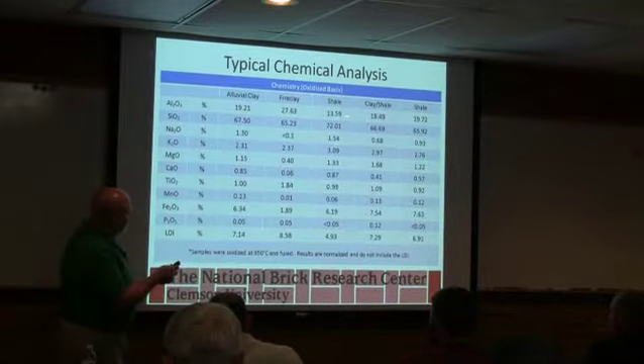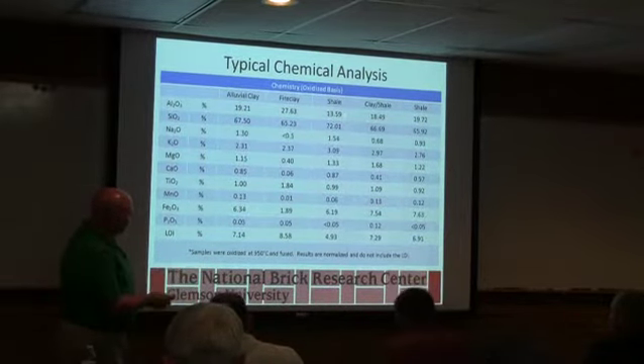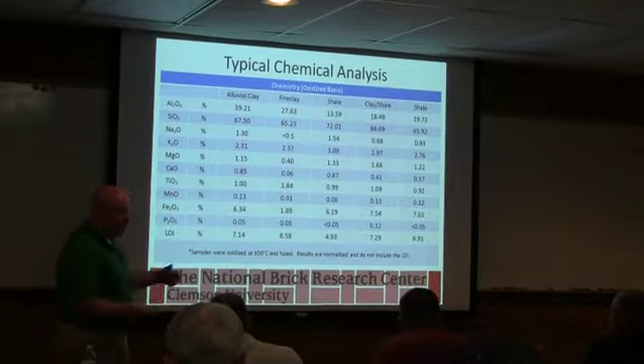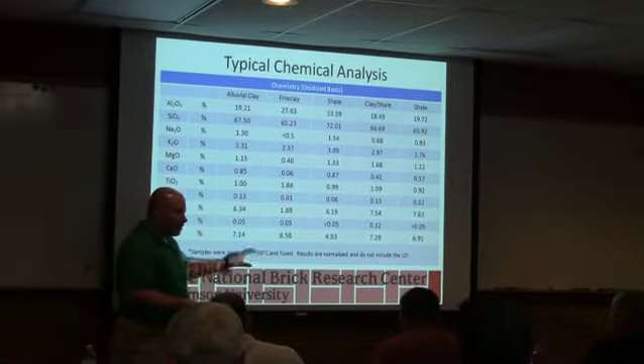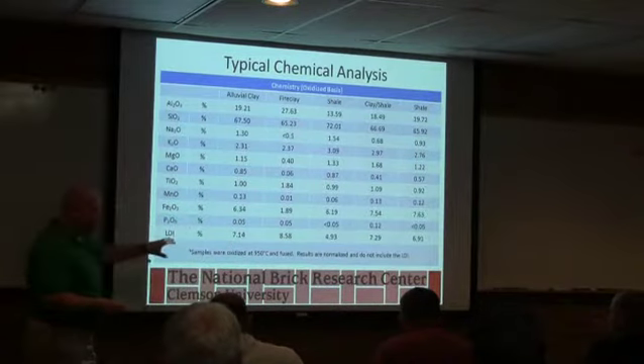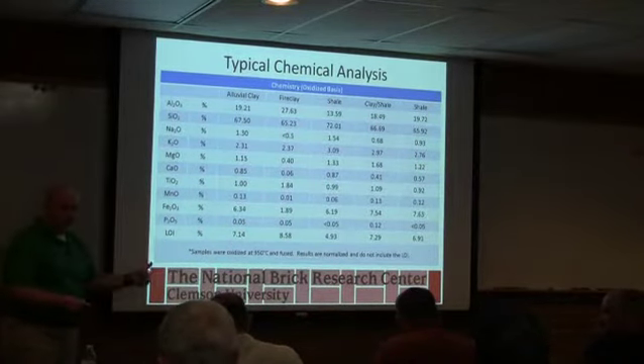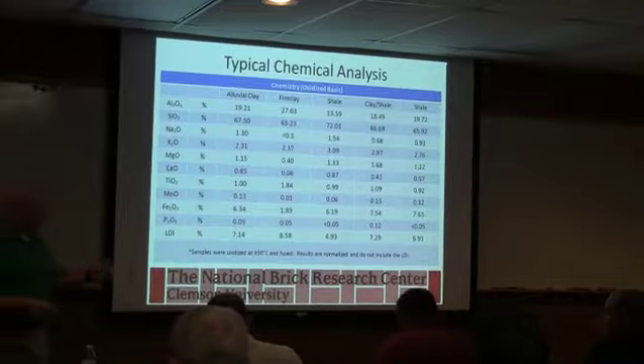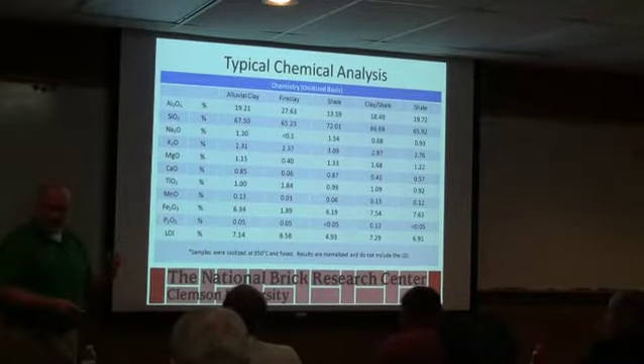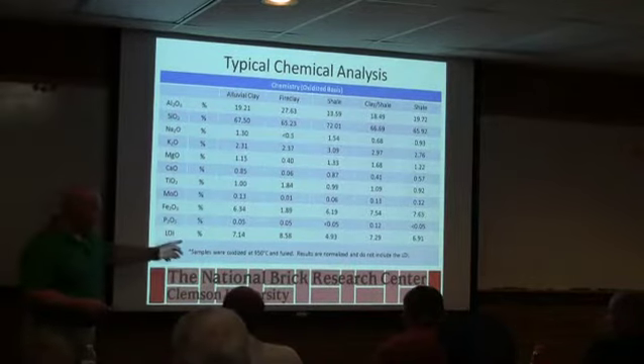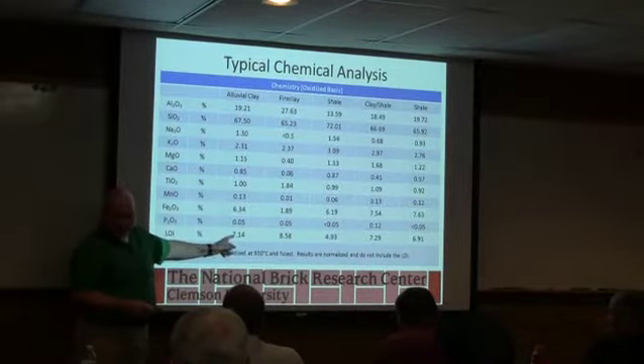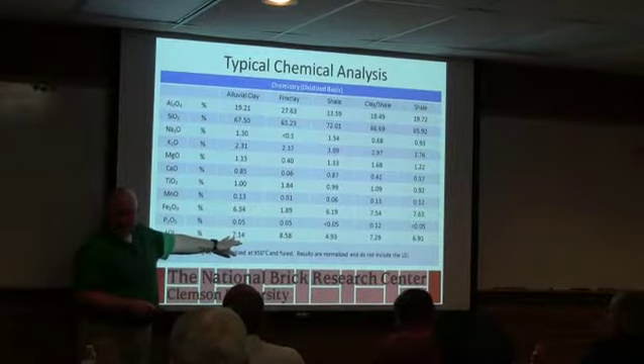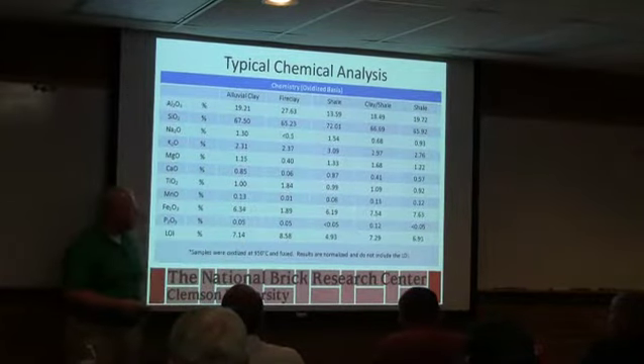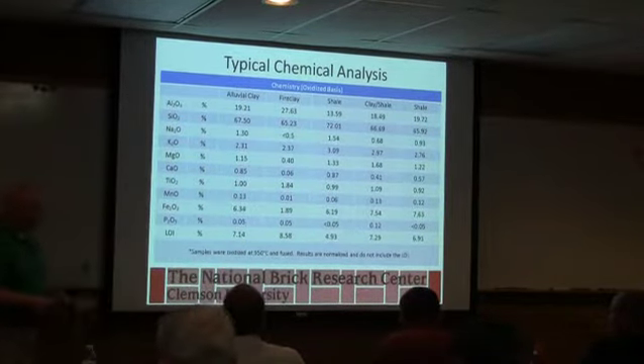The one I said was probably not very plastic also has a low loss on ignition, meaning there's probably not a lot of clay mineral. So the clay mineral contributes the most to that number, but it can also be carbon. Pure limestone, if you heat it up, loses 44% of its weight. So it doesn't take a lot of limestone to make this number really big. So that's another thing we watch to see if lime pops may be a problem. It could be organic carbon.